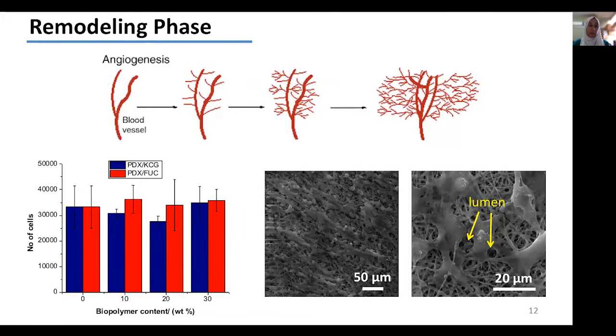Therefore, to look at whether the scaffolds were promoting angiogenesis, we seeded endothelial cells on the scaffold. And the graph on the lower left-hand side indicates that the cells proliferated very well on all the scaffolds, and the cell number remained practically the same on all the different scaffolds, irrespective of the biopolymer content and on the nature of the polysaccharide. The scanning electron microscope image was in line with the MTT results, where we noted a very high number of cells on all the scaffolds.